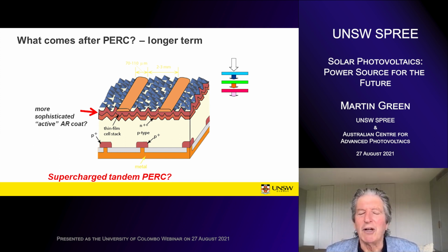But in the longer term, there's a way of getting even higher efficiency, so higher than the 27%, which I think is the limit for a single cell. If you stack another cell on top of silicon, you can actually perform better than with a silicon cell. A silicon cell, as I mentioned before, is a photon converter. You get 1 photon in and ideally 1 electron out. So you're doing really well if you get 1 electron out. It's generally a fraction of an electron per incident photon, so you need more than 1 photon per electron out.